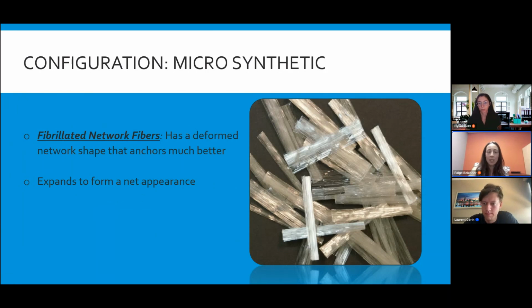But then for the next slide, as we get into more commercial projects and that type of work, we have this fibrillated network fiber option, and it definitely will anchor better into the concrete, similar to a fishnet. As it pulls apart, we could see that these networks hold the concrete together. This is what can be used to replace some light duty mesh. Super light duty, we would dose this around 1.5 pounds, and there are two standard lengths, 3/4 of an inch up to 1.5 inches. And essentially, we can replace very light duty wire mesh, strictly there for maybe temperature and shrinkage control. And if anybody happens to have questions on where this would best be used, feel free to write it down.